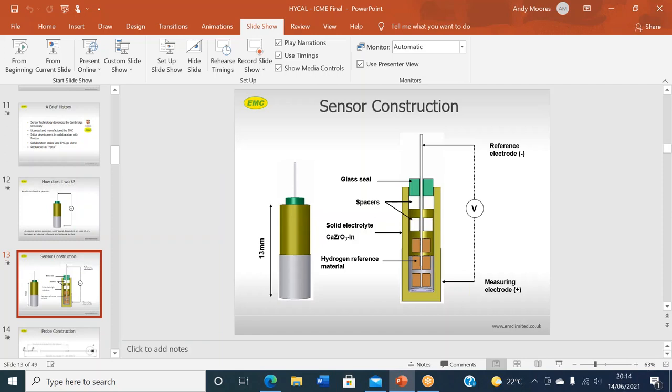Okay. Another question: I know this depends solely on the alloy and the application, but roughly speaking, what's the rough hydrogen level that you would get to before you start generating things like gas porosity? It depends a little bit on the casting process, but generally if you're around 0.1 level, then you'll be fine. If you get towards 0.15, 0.2, you run the risk. That's millilitres per 100 grams. Get towards 0.2, you might be expecting some problems. But if you're a die caster and want a bit of hydrogen to counteract shrinkage, then that 0.2 level might be what you're aiming for. So it does depend.